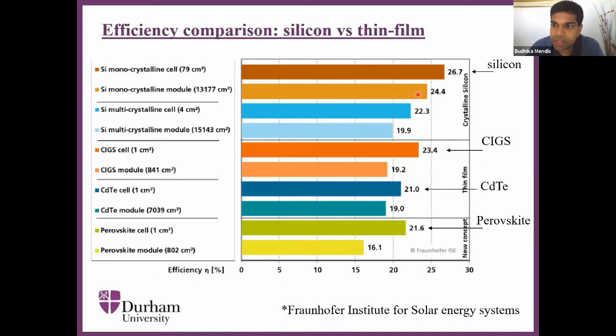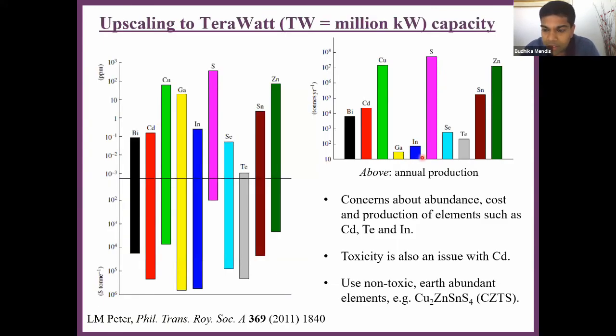So this slide here shows how thin film solar cell materials such as CIGS and CdTe compare with silicon. Silicon, currently the record efficiency at the cell level is roughly around 27%, whereas in the case of thin film technologies, you are at the level of around 23 or 21%. You might think that the difference is negligible, but remember, a silicon solar panel has a lifetime of something like 25 years. So even a 1% improvement in efficiency over 25 years leads to a significant difference. So there are issues in terms of efficiency that is limiting the more widespread adoption of these thin film solar cell materials. But we also have other issues that we need to consider.